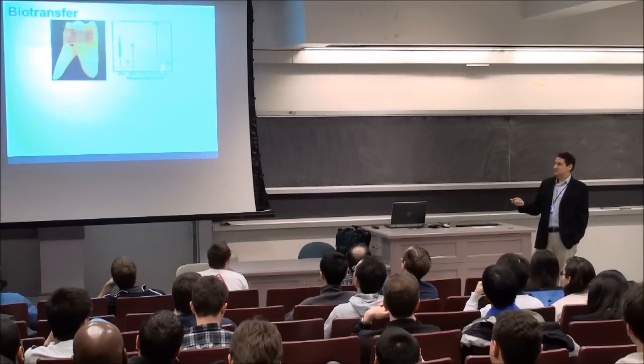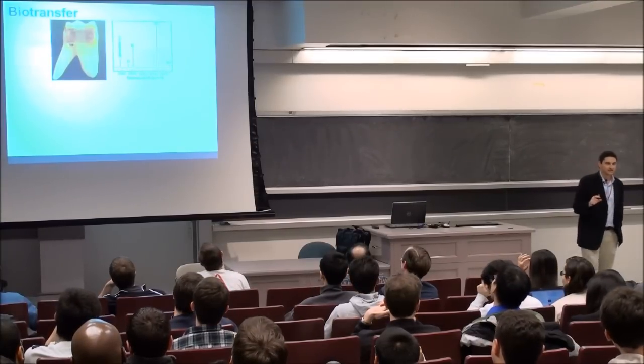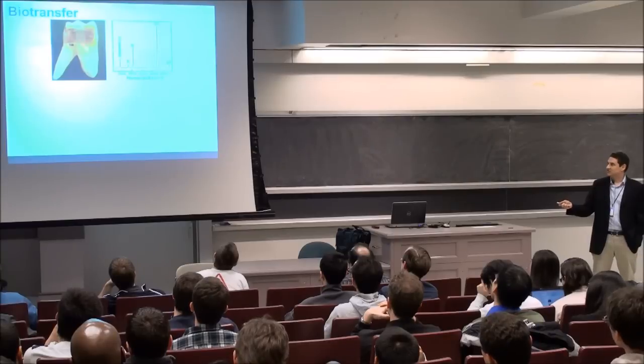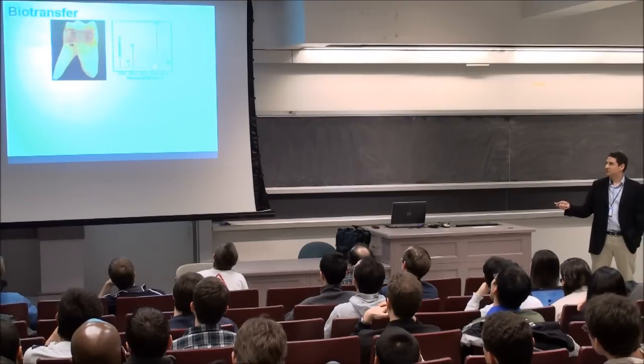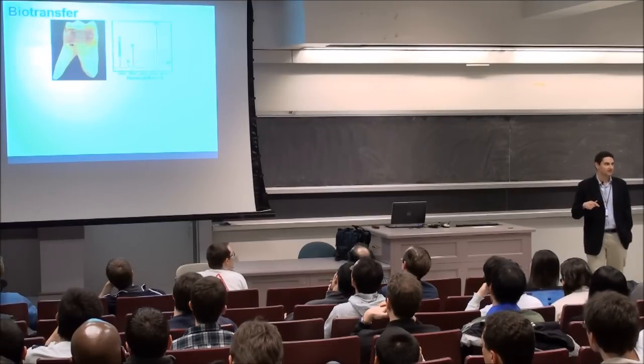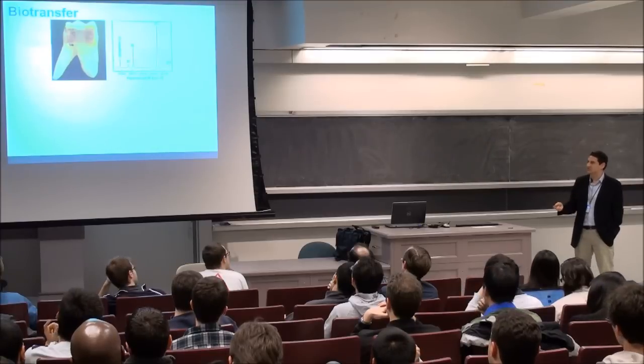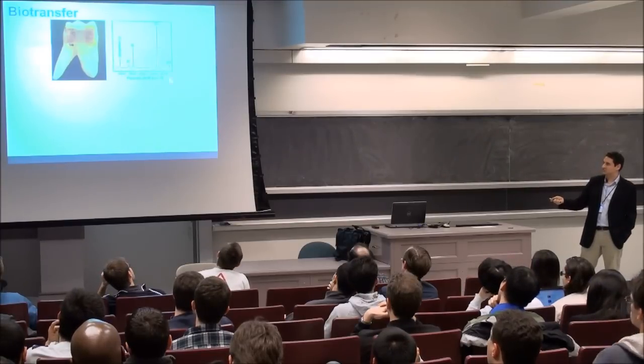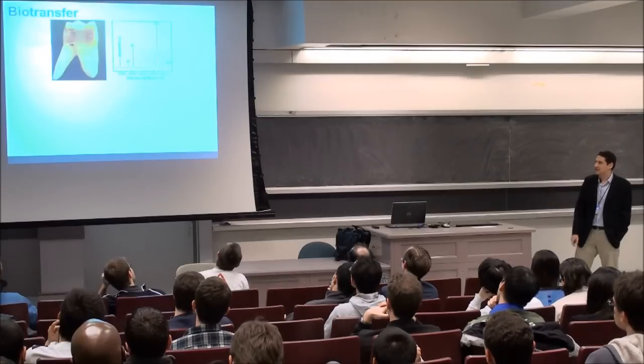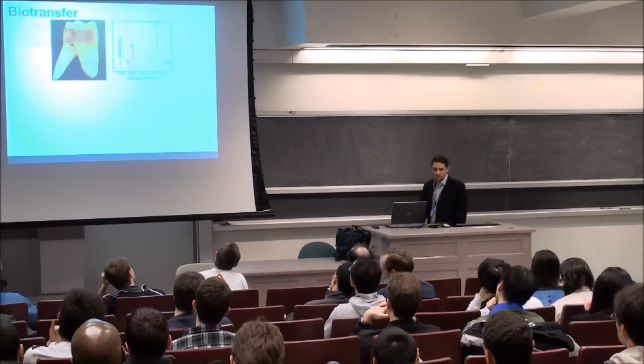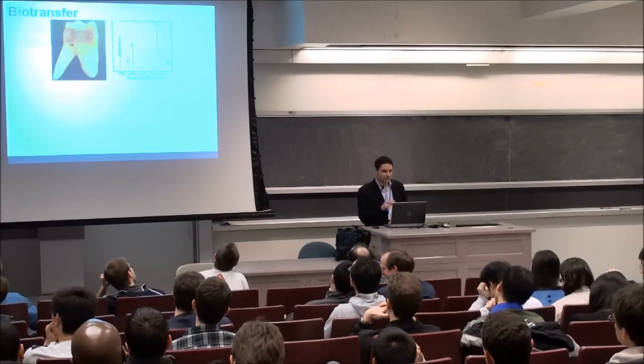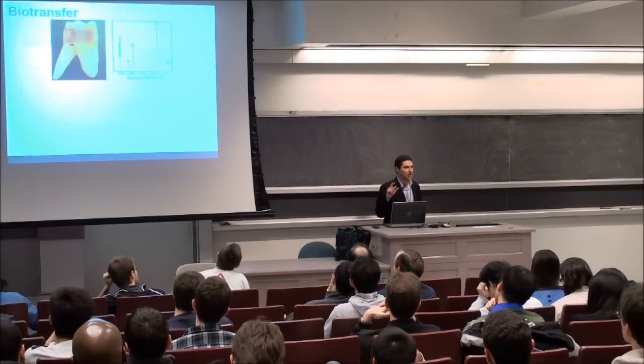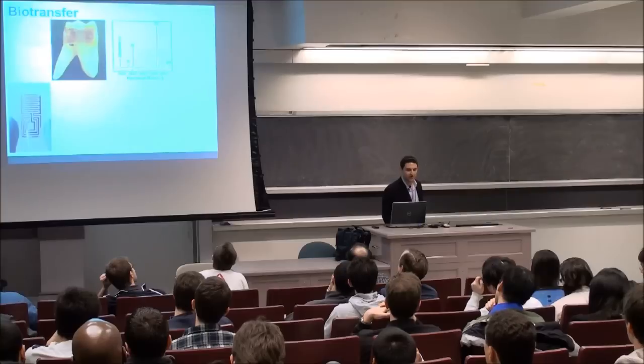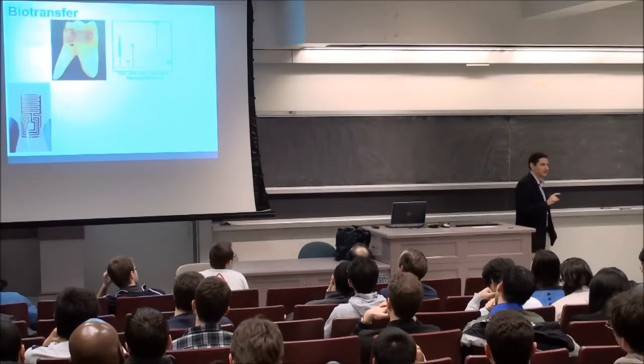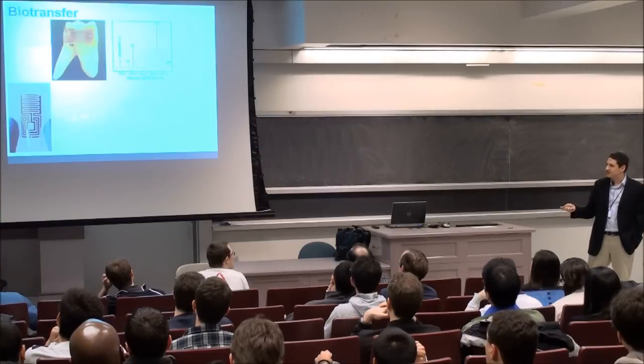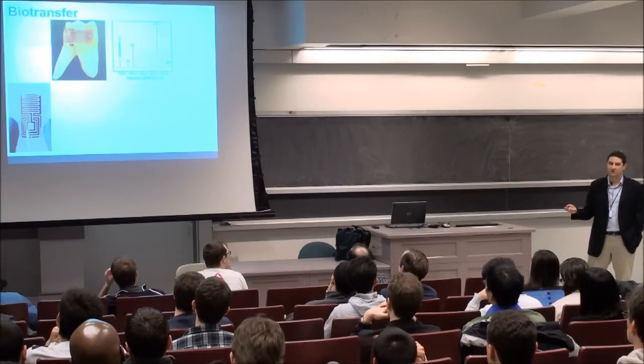But basically, we took his tooth here, and we printed this graphene onto the tooth. And you can see here, here's the graphene with electrodes here. And you can do Raman spectroscopy on that tooth. In fact, the tooth's peaks in the Raman spectrum are distinct from the graphene peaks. So you can see clearly the monolayer graphene 2D and G peaks there on the tooth. But of course, this doesn't have the wireless coil on it. The problem with the wireless coil is that we couldn't find a good way yet of miniaturizing it. So it actually added a fair amount of space to this overall device here.